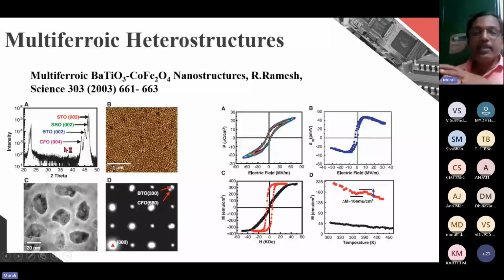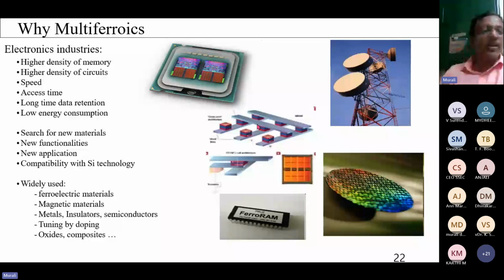What I want to insist here is that this thin film has both electrical polarization and magnetic polarization. So this is both ferroelectric and ferromagnetic. And also, if you change the temperature, the magnetization changes along with the ferroelectric polarization. So there is quite a good elastic coupling between the ferroelectric and the ferromagnetic materials. Okay, so now we can have, not in a single phase material but in a single thin film, a material with both ferroelectric and ferromagnetic properties. Why do we need multiferroic materials? Because they can produce a very high density of memory, that is, a higher density of circuits.